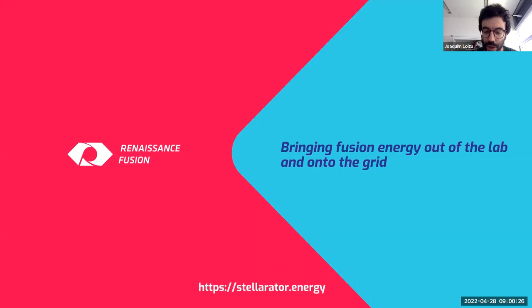So it's again the liquid metal walls that form a panacea for many of the issues, because the liquid metal itself doesn't have an issue with power density per square meter because it's flowing and you can increase it, of course, within limits, but that limit is much further away than if you have a solid plasma facing component. Right. So you don't need any specific design or scenario development for detachment.